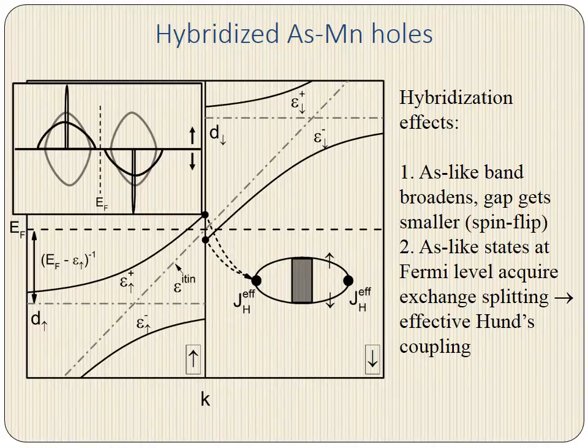Now, this classical view of the double exchange cannot be strictly applied to our system, as the moments and holes are of different types. Remember, the moments are manganese, but the holes are of arsenic character. Therefore, we're going to need to modify our view a little bit. So again, we'll begin with a manganese atom that is Hubbard split into spin majority and minority bands by a value U.